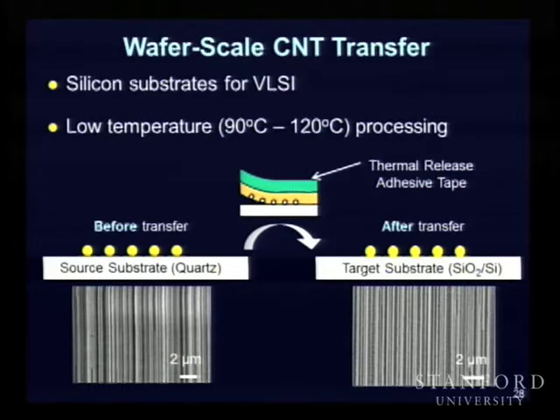So you transfer these carbon nanotubes on layer 1, create your imperfection-immune circuits, build a dielectric, and then since it's a very low temperature process, you transfer your carbon nanotubes on layer 2, build your circuits, layer 3, build your circuits and keep going. That gives you the monolithic 3D circuits out of these carbon nanotubes. I'll show you some pictures of that later. So this transfer step, we found it to be very useful.